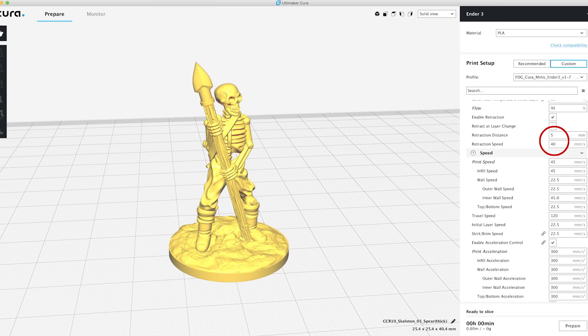That's going to wear a certain length of filament down more from that feeder gear grinding into it, and that can actually lead to under extrusion. So I don't like to have very long retraction distances. It's just something I found that creates more hassles than it's worth. So for me, the best balance is 5 millimeters of distance and about a 40 millimeter speed.